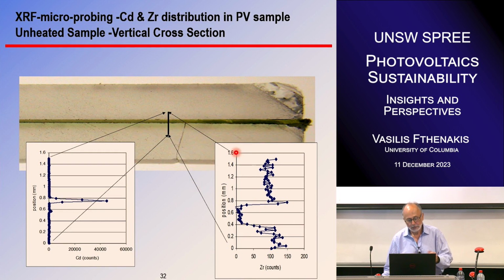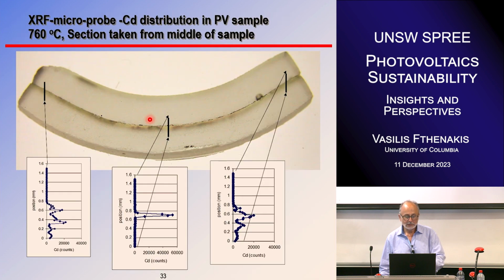This is zirconium, that's a precursor, an element in glass. So this is before it's heated. Now, when it's heated, this is 760 degrees Celsius. It is above the softening point, but below the melting point. So you can see that the glass took the shape of the semi-cylindrical container. And we have the same signature here, about 50,000 counts as before, just a verification that cadmium is there.